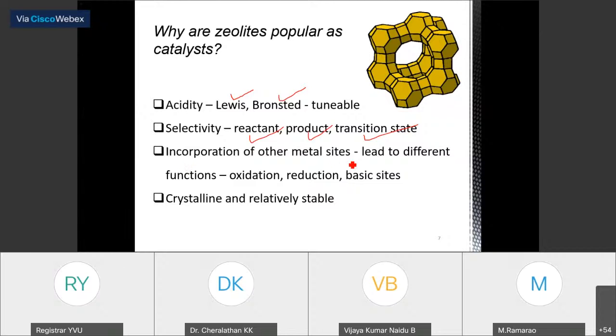I told you that zeolite will have only silicon and aluminum, but you can replace aluminum or silicon by other metal sites, and in this way you can incorporate different functions like oxidation, reduction. Even basic zeolites can be prepared by playing with the kinds of metals added to the zeolite structure. And finally, they are all crystalline. They are very stable at higher temperatures. So due to all these properties, zeolites are popular as catalysts.